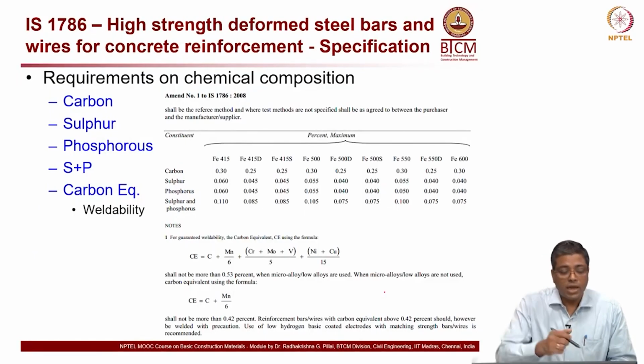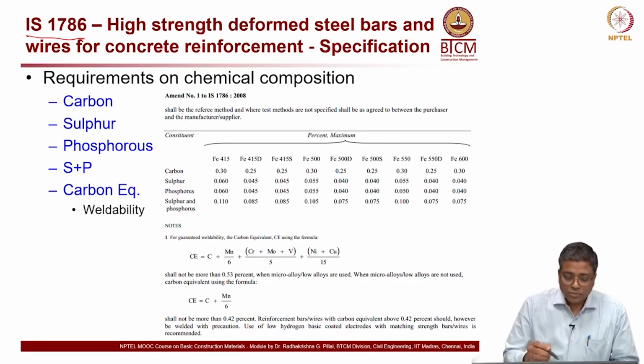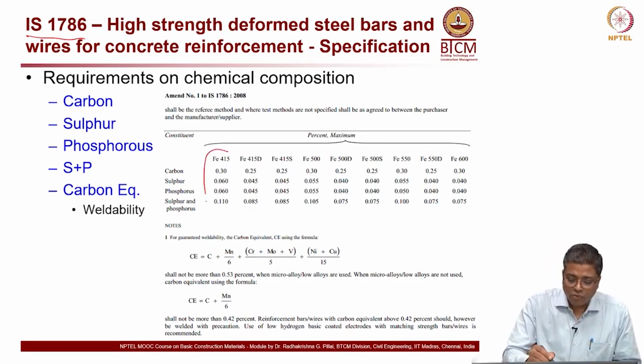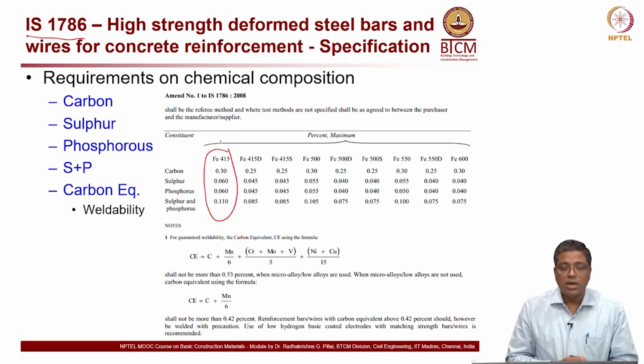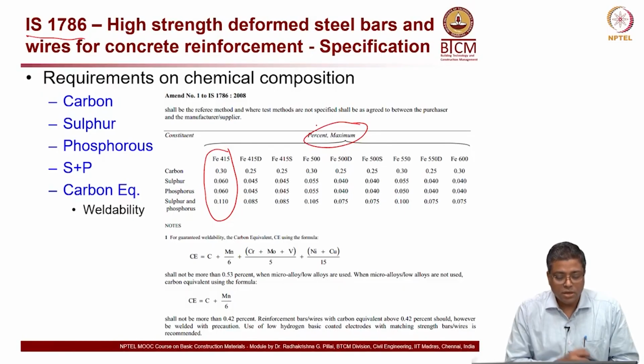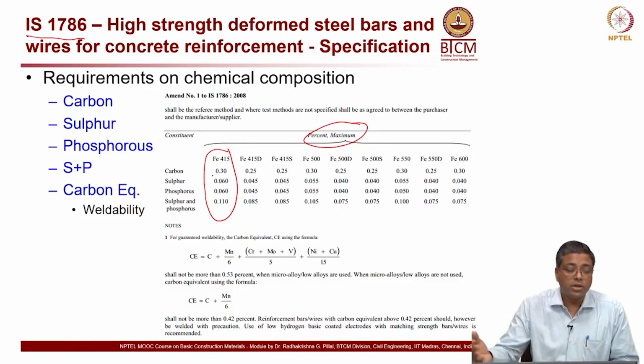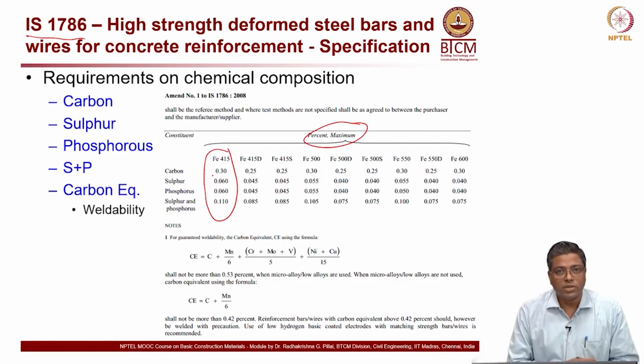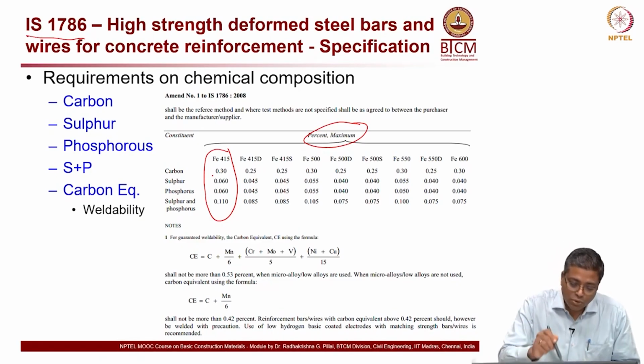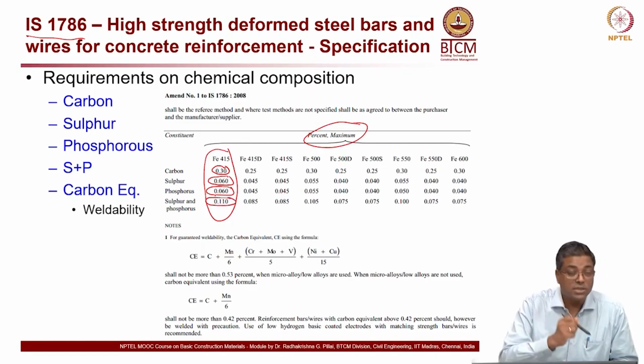Now, for this again IS 1786 has some specifications. They say for Fe 415 steel, this should be the maximum or upper limit for various chemicals. If you have carbon content more than 0.3%, then you cannot call it Fe 415 steel. So, you have to make sure that the carbon content is less than 0.3, the sulfur content is less than 0.06, phosphorus is less than 0.06, and sulfur plus phosphorus is less than 0.11.